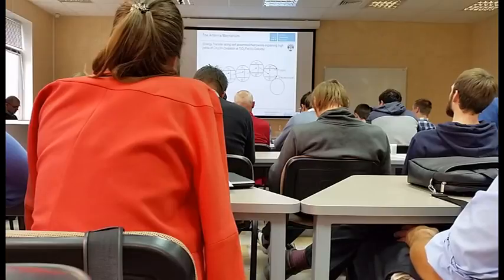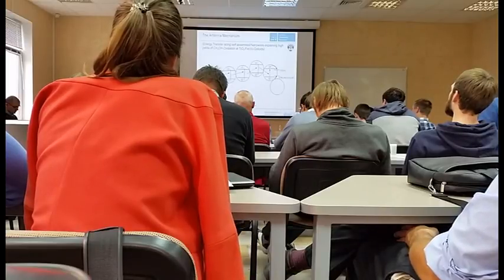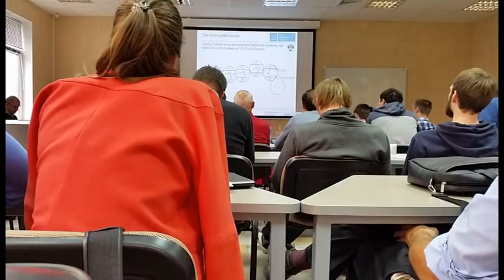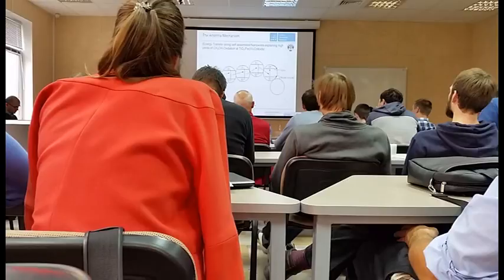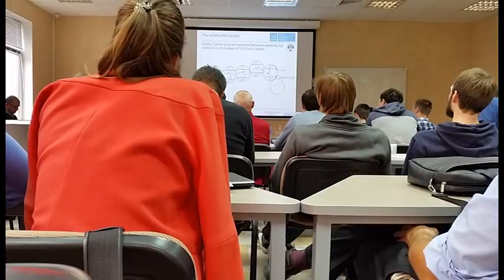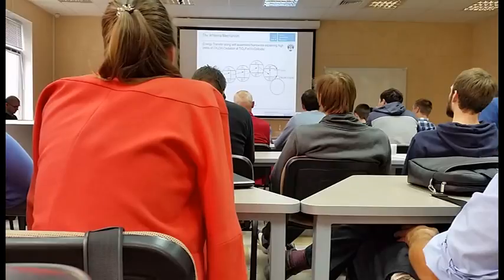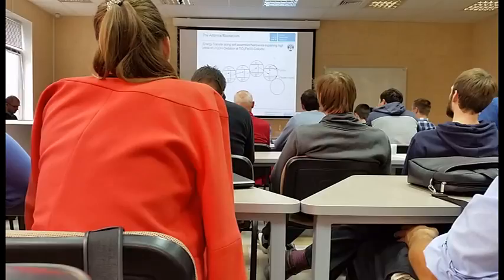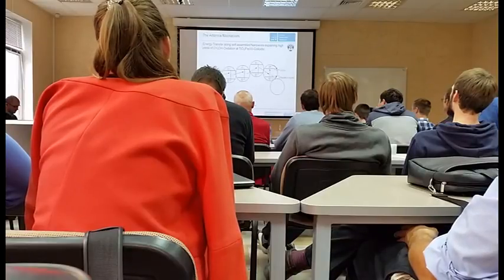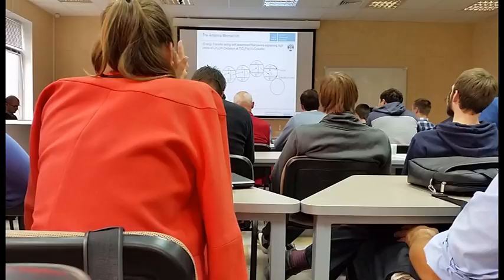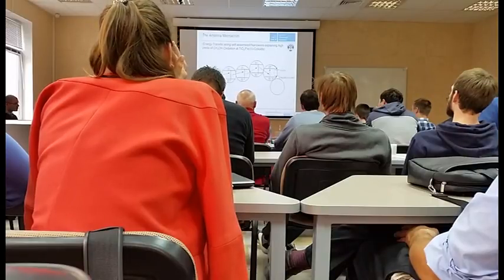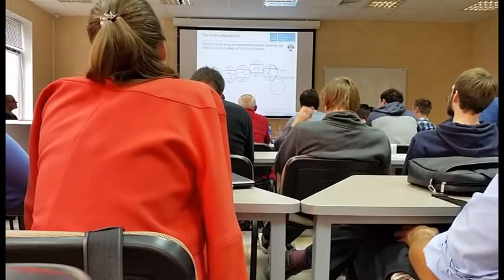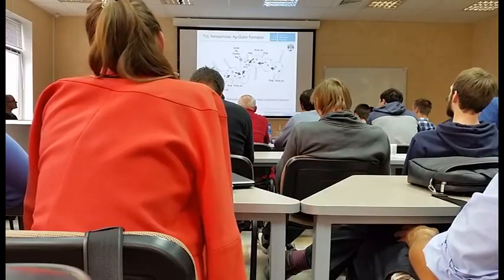What we are pretty sure of is that you should not neglect something like an antenna phenomenon, very well known in many other chemical and photochemical systems, where one particle might absorb the light. You can have an exciton transfer through a three-dimensional network of these self-assembled nanoparticulates until finally you find a structure where you have the right conditions for the surface reactions to occur, here shown as a surface reaction for the oxidation of methanol and the reduction of oxygen.